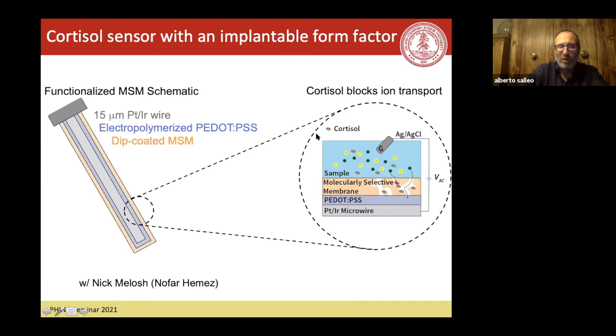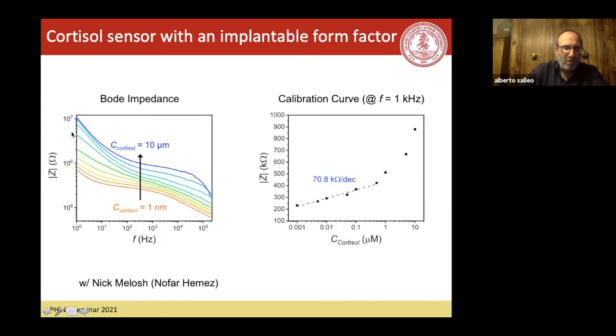So then you'll have another electrode somewhere else that will put a voltage, and you'll measure the impedance between the gate electrode and the PEDOT:PSS actually, and the platinum microwire. And so if ions cannot make it through, the impedance of this whole system will go up. And this is how it works. If you measure the impedance as a function of frequency, you can see that systematically, as you increase the concentration of cortisol, the impedance goes up.